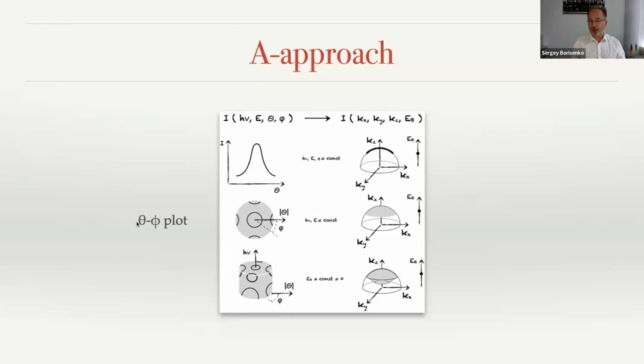When one does what we call a theta-phi plot, this is now native to the method. This is the angular distribution, a polar plot. Remember, two angles. You represent the data in polar coordinates with a color plot. Normal is 0. This is natural for the method. This is the angular distribution, and again it has a transparent physical meaning: it is the intensity distribution on the emission sphere in 3-dimensional K-space.